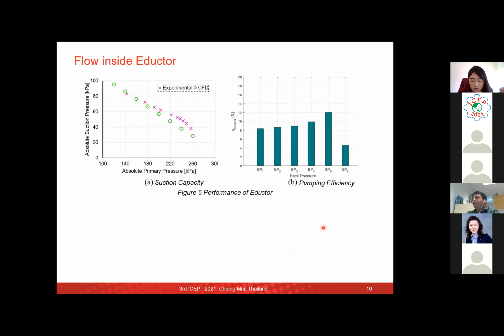So this is the basic primary result, where we are talking about the capacity of the eductor to be implemented in the water desalination process. The first criterion is the capacity to create sub-atmospheric pressure conditions. We can see that with increasing primary pressures, the absolute suction pressure is decreasing, and experimentally we were able to achieve up to 40 kPa absolute pressure on the eductor that was experimented.